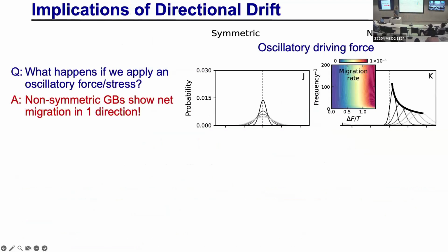Okay. Let's make it a little bit more interesting. So if I put on a driving force to the left and say it moves faster to the left, and when I switch the driving force, make it move to the right, if I oscillate the driving force, like put on a stress that's oscillatory, the boundary will have net motion in one direction if it's non-symmetric. So this is the distribution. You can see it's spreading in that direction when you put on an oscillatory driving force. And if it's symmetric and you put on an oscillatory driving force, it doesn't move on average. Okay? So that's kind of interesting because it suggests ways we can move boundaries.